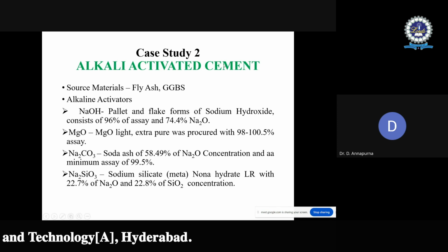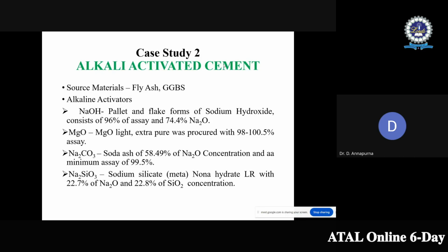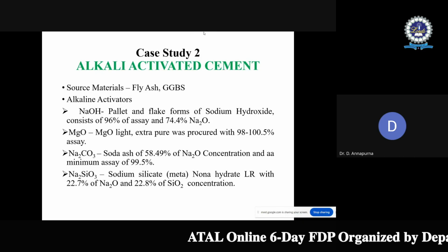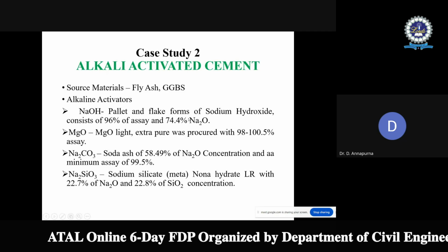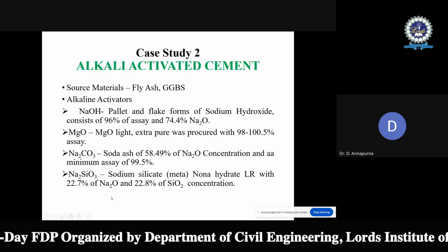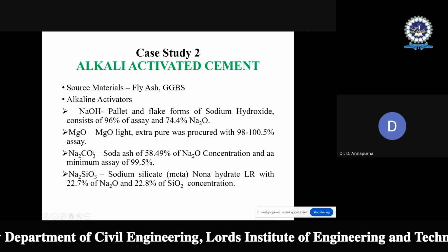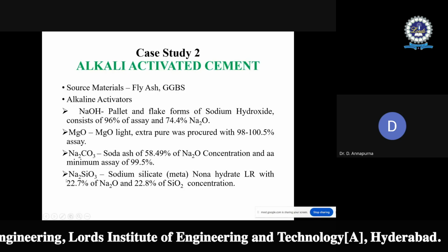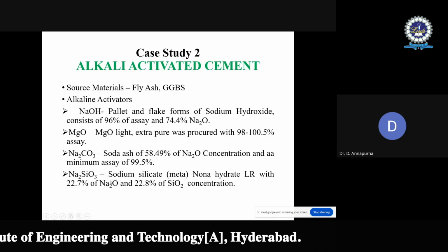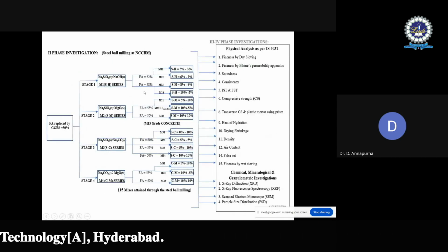In the earlier work, the concrete was prepared. Here, the cement is prepared, that is, a dry powdered form of alkali activated cement. The source materials used here are fly ash and GGBS. To prepare the alkali activated cement, alkaline activators are varied, like sodium hydroxide, magnesium oxide, sodium carbonate, sodium silicate. The materials were taken in different combinations. This is the complete work.